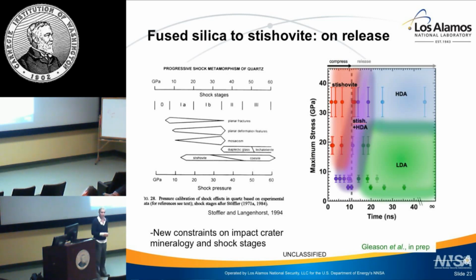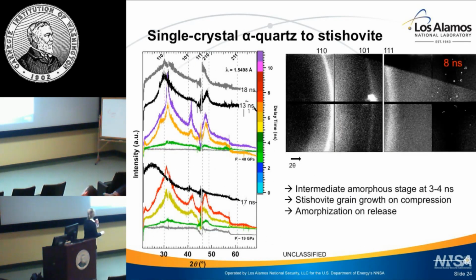We also look at quartz, okay, so this is just a preliminary data set. Again, we have intensity as a function of 2 theta. Now I orient my single crystal quartz such that I do not burn a hole with the Laue pattern, the bright spot of quartz, in the CS pad. So you'll see my gray traces here, so 0 time delay. We don't have any bright spots, right? So that's done on purpose. I don't expect to see anything.